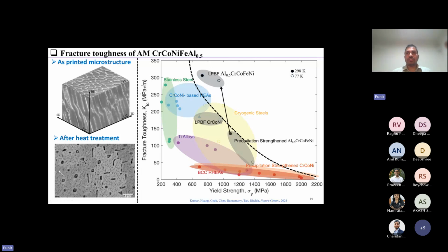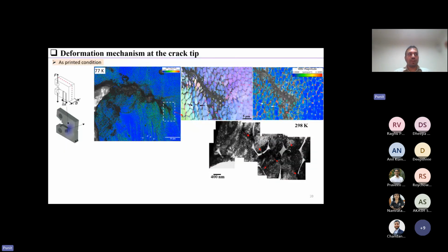So what is so special about this microstructure that is giving such high fracture resistance to this material? To understand that, we take one CT sample and section it from the center to expose the region of high stress triaxiality. And in this region, we did EBSD and strain mapping. Looking closely at this crack tip, we see that these misorientation bands you can see here are emanating from the crack tip and traveling further away from the crack tip, almost around 200 to 300 micrometer.